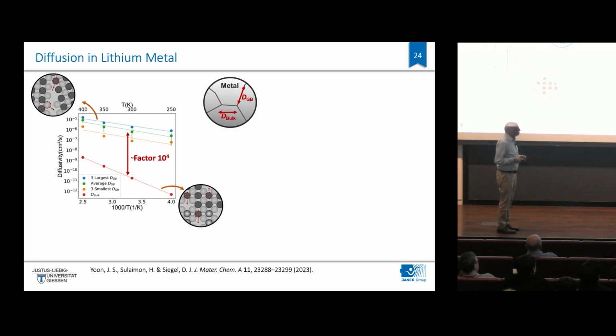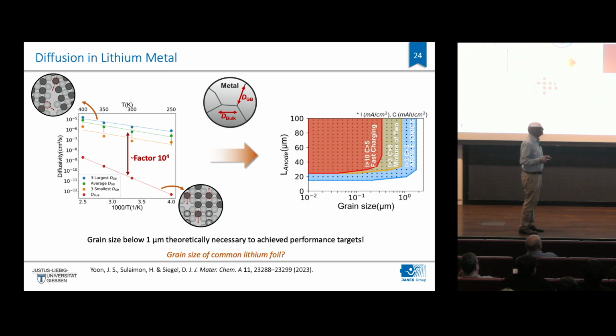There was a very nice paper by Don Siegel, a theoretician from Austin, Texas, who calculated the diffusion of lithium metal. What is shown here is the diffusivity of lithium in grain boundaries and in the bulk of lithium. And he calculated that the diffusion coefficients are much, much higher in grain boundaries. And he even calculated then, okay, what should be the ideal grain size of lithium metal to have enough grain boundaries to have fast transport in the lithium metal? Well, it's clear. If the grain boundaries are fast, you make a nanocrystalline material and you have a very high diffusion rate. And he calculated, well, it should be below 1 micron grain size.